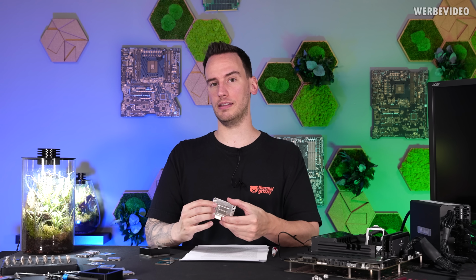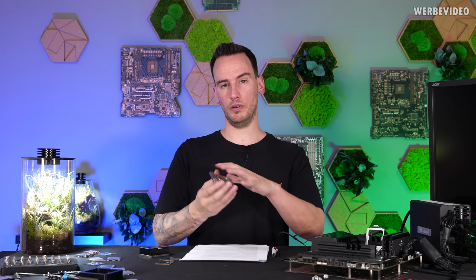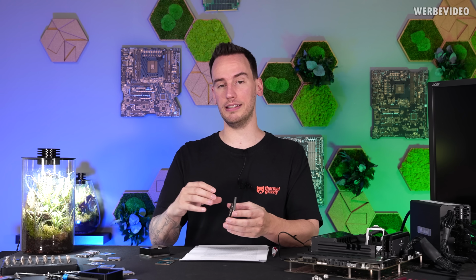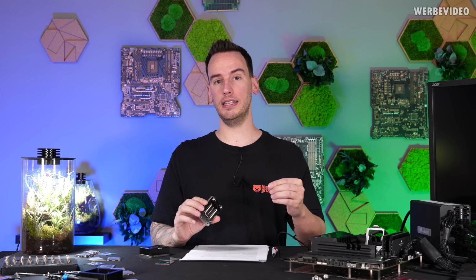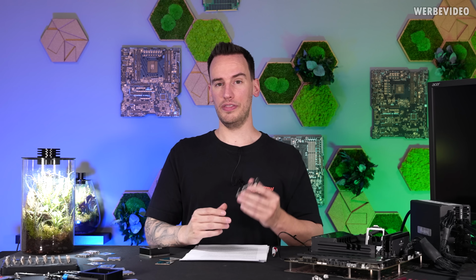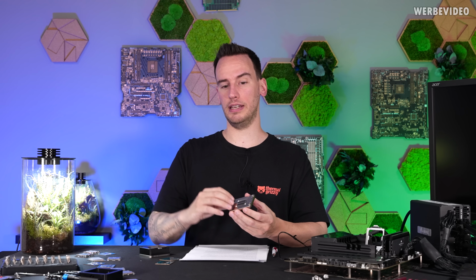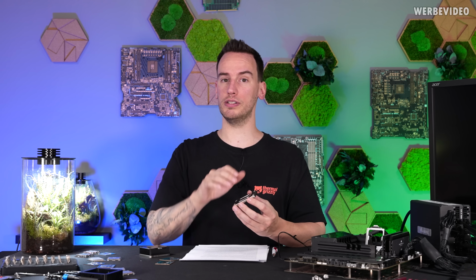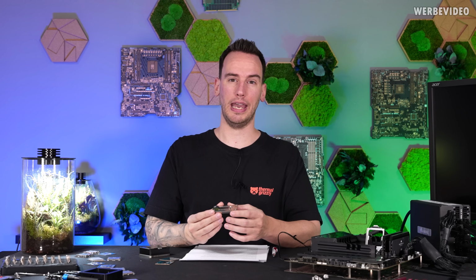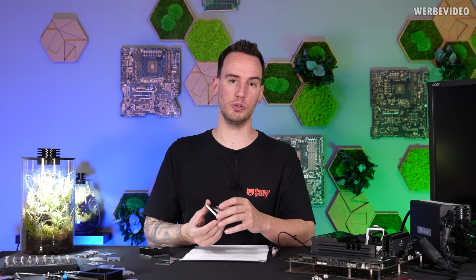The amorphous structure has some benefits, and that's the uniform type of the coating, which also has a higher density, and due to the uniform particle distribution, it also has a uniform thermal conductivity, which is and can be a benefit. Due to the higher density, it also has a better protection, and it's harder, and it just provides better corrosion resistance against gallium. The crystalline structure caused by electroplating, on the other hand, is softer. It has a defined crystalline orientation, and thus the thermal conductivity depends on the crystal orientation, how good and how bad it can be. And it's not as good as the chemical nickel when it comes to corrosion resistance.